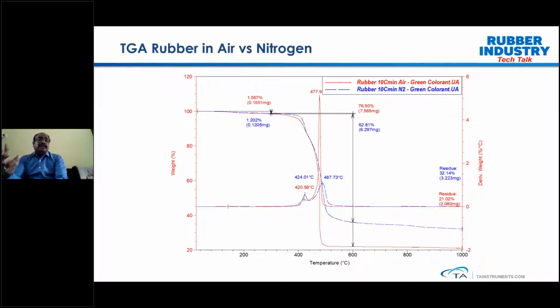So what this signifies is that furnace control is very, very important. That's where we need to be very careful in selecting the TGA, in how well the furnace is going to control the atmosphere. And the gas switching also needs to be very fast and efficient. So this analysis shows how much the atmospheric condition, either air or nitrogen, has an impact on the decomposition kinetics.